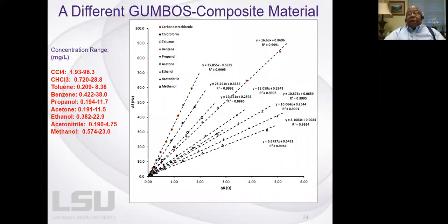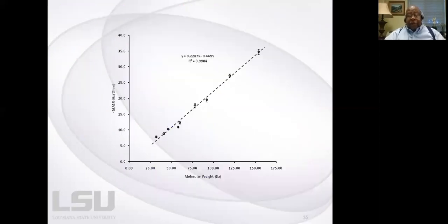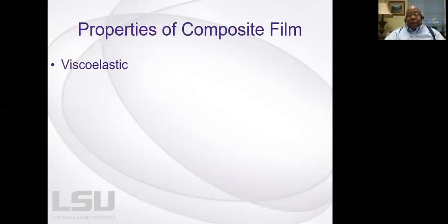So if we use a different composite material, you still get that linear relationship, and you still get the delta F over delta R related to molecular weight. So it's not just unique to the particular composite that we use. There are a number of different materials which will give you this molecular weight information. And the property that is required is that the material must be viscoelastic.